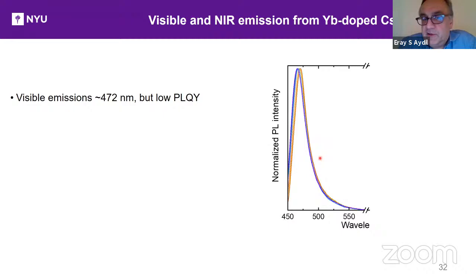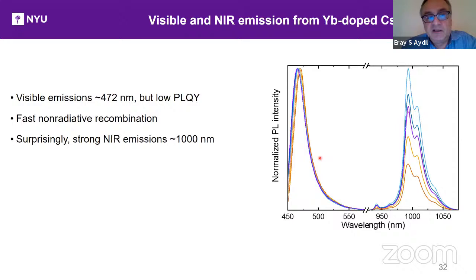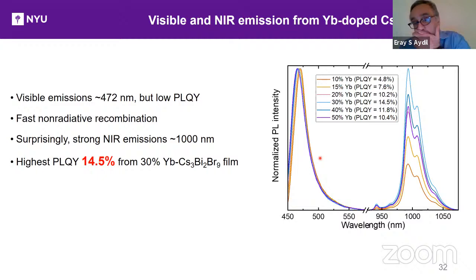So first, visible emission. They do emit at 472 nanometers. So the visible emission is there, but the photoluminescence quantum yield is too low. So very fast non-radiative recombination, lifetime less than one nanosecond, faster than we can measure. So there are lots of defects and they are non-radiatively recombining the excitons, okay? But surprisingly strong near-infrared emission at 1000 nanometers, where we would expect. And in fact, you can quantify the photoluminescence quantum yield. It increases with increasing ytterbium, and the highest we get with these films is 14.5% from the 30% ytterbium doped cesium-3 bismuth 2 bromine 9 film.